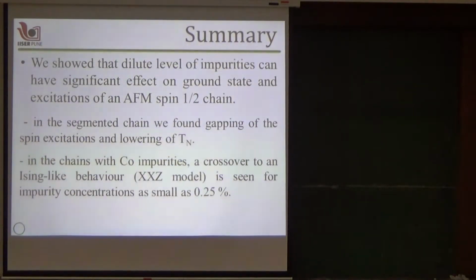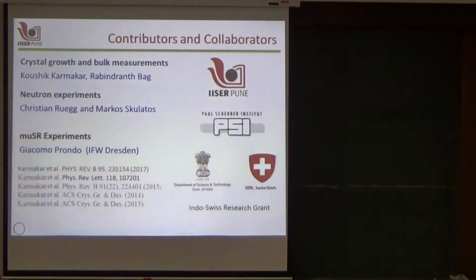We showed that dilute levels of impurities can have a significant effect on the ground state and excitations. So in the segmented chain we found gapping, and we see that the TN is lowered, whereas with cobalt impurities we believe cobalt has on-site single ion anisotropy, which is getting induced to the entire chain, and that leads to this crossover.